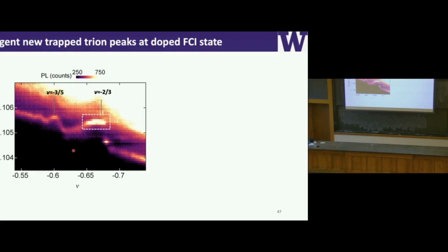The first thing I want you to pay attention to is that when I dope my system to 2/3 filling, you will see there's a plateau feature. In this spectrum, the vertical axis is the energy of my trion luminescence, and the horizontal axis is my doping. So when I dope the system to this 2/3 fractional state, a plateau appears. If you're familiar with transport, when you do transport on a fractional quantum Hall state, you see a quantization plateau in the Hall conductance. But here it shows you a plateau in the emission energy. It means I do have an incompressible state in the system because I enter into this 2/3 FCI state.